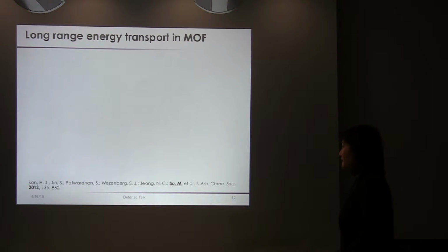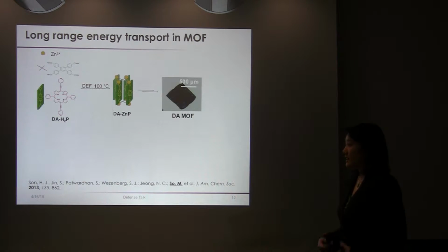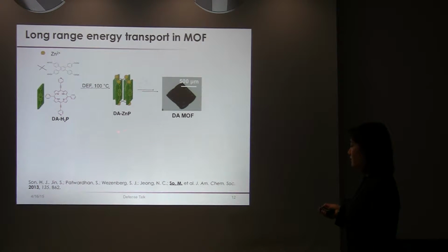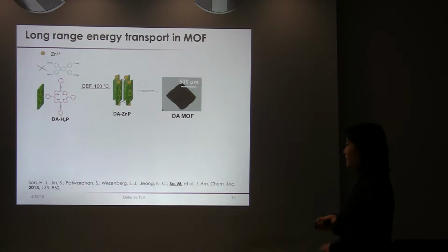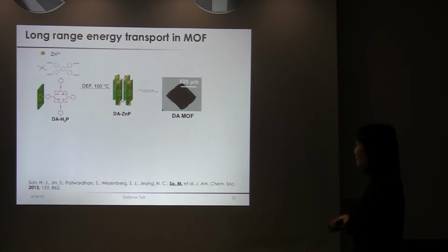So my colleagues and I had essentially tried to assemble a DA MOF out of this dipyridyl-based porphyrin linker with this tetracarboxylate-based organic linker, as well as zinc nitrate hexahydrate and diethyl formamide at 100 degrees Celsius to form these zinc metallated porphyrin-based MOF. And essentially the DA MOF was formed, and it's a plate-like green crystal.